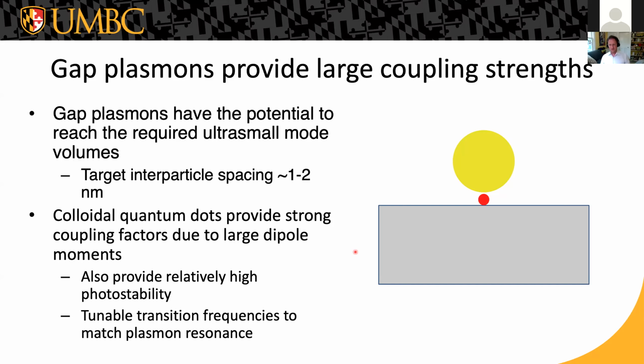If you make it much smaller than that, then you start to get issues with charge transfer and electron tunneling and Landau damping. So we need a little bit of space to keep the systems isolated from each other. And we use quantum dots in this system. Other people have used single molecules in a very similar configuration to reach the strong coupling regime. Molecules are smaller than quantum dots, so you do lose a little bit in terms of how small your mode volume is when you use quantum dots.